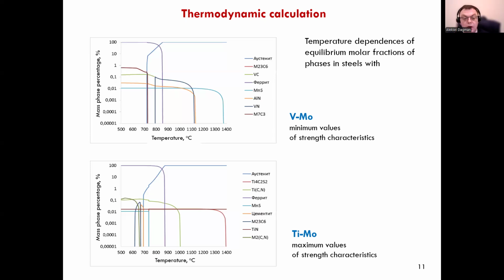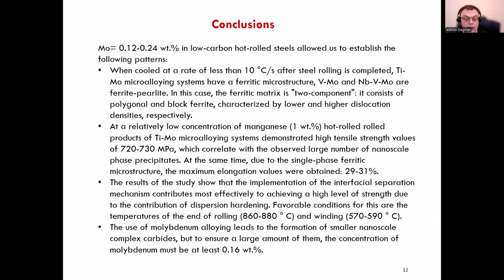Analysis of the results of the study of steel microalloyed with titanium and molybdenum shows that steel with a low carbon content and higher strength was distinguished not only by a high concentration of molybdenum. In the production of hot rolled products, higher temperatures of the end of rolling and winding were used: 870 degrees centigrade and 580 degrees centigrade, respectively.